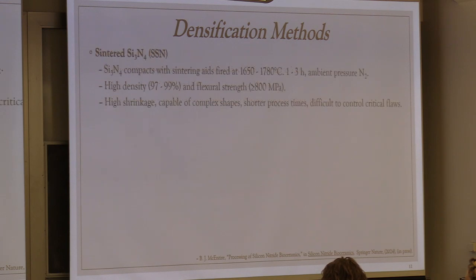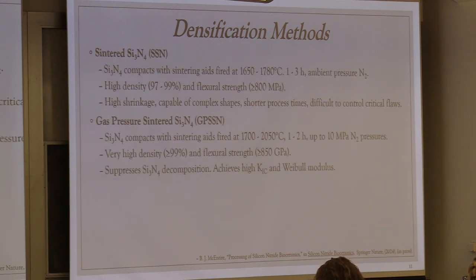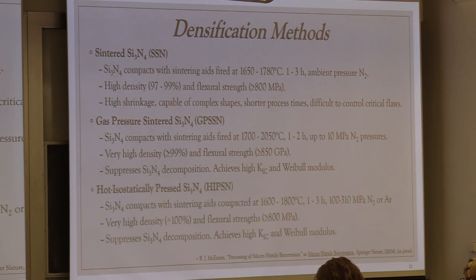And then proceeding on, the next one was actually sintered silicon nitride. So people said, okay, we need to figure out how to sinter it at ambient pressure conditions without hot pressing. And so this actually took the form of more additives, a lot of experimentation in the 70s, 80s, and 90s on this. But the unfortunate thing about this, it did give good properties, particularly at room temperature, but not necessarily at high temperature.